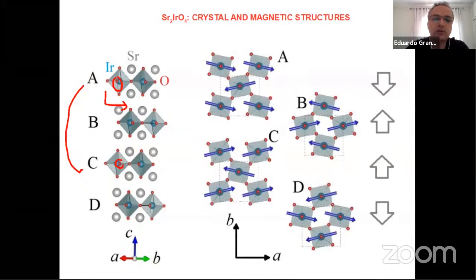nowadays. So now if you look at the magnetic structure of this material, I mentioned that you have these layers A, B, C, and D. Now if you look at these layers from the top view, from the C-axis, you see squares. You see the iridium atoms, and these arrows represent the magnetic moments of the iridium. And you see that the magnetic structure is not a collinear magnetic structure. Since I mentioned before that you have this tilting pattern of the oxygen octahedra, this tilting pattern also leads to a rotation of the magnetic moments of iridium that follows this tilting pattern of the oxygen octahedra.